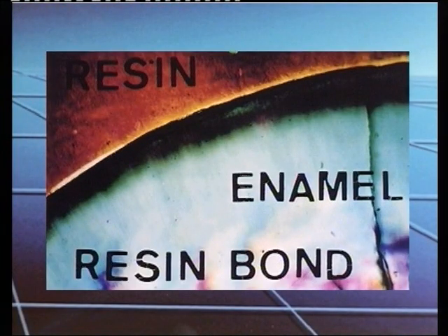The adhesion of composite to enamel with a resin-based bonding system creates stress at the restorative interface. This is confirmed by the birefringence present when viewed under polarized light. When a composite resin and resin-modified glass ionomer bond are co-cured to the enamel surface, the slower setting glass ionomer sets after the polymerization shrinkage of the composite and no stress occurs.